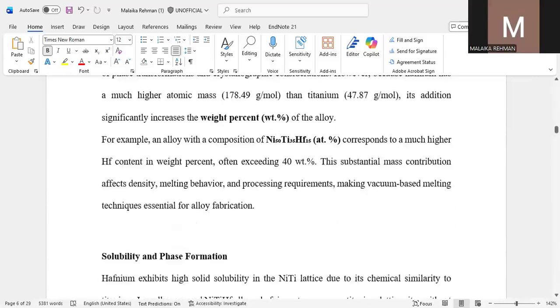For example, we have taken an alloy with a composition of nickel 50, titanium 35, and hafnium about 15, which corresponds to a much higher Hf content in weight percentage, often exceeding 40% by weight. This affects the density, melting behavior, and processing requirements, making vacuum-based melting techniques essential for the alloy fabrication.